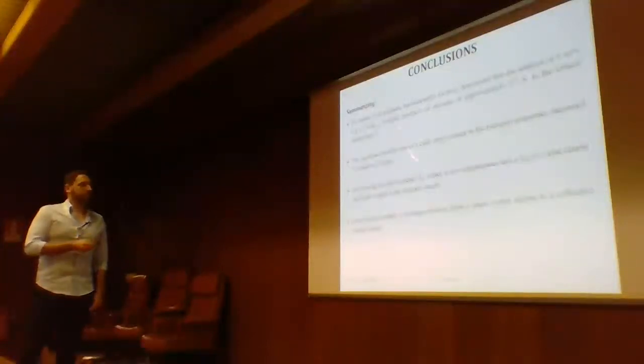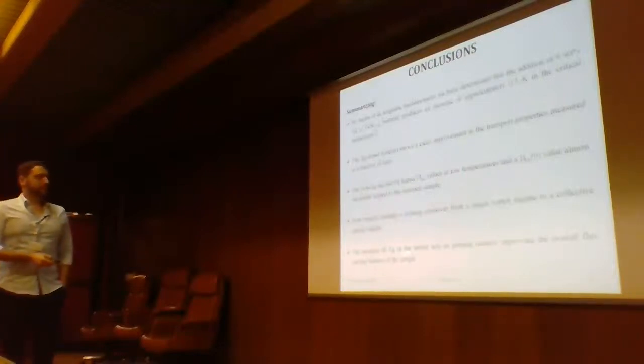In particular, both samples undergo a pinning crossover, as we have seen, from a single vortex regime to a collective pinning regime. So finally, we can conclude that the presence of silver in the lattice acts as pinning centers, improving the overall flux pinning features of the sample.